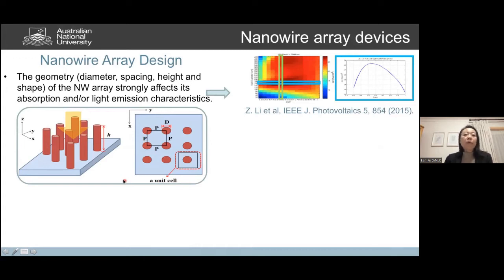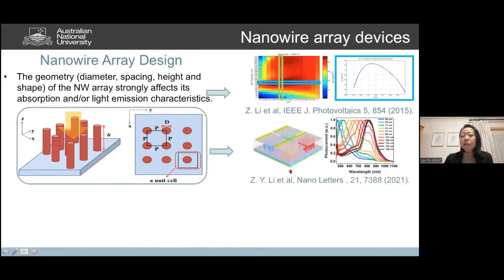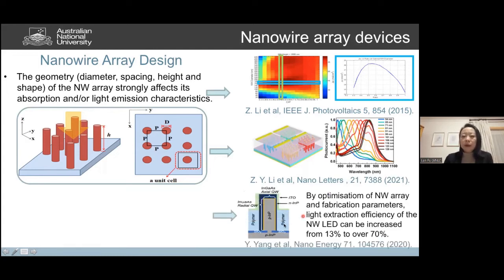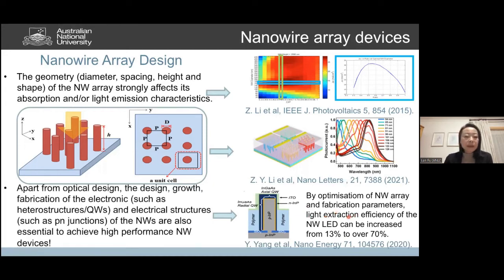We do numerical simulation to design nanowire arrays with good absorption, to achieve broadband absorption in solar cells. We've also shown that by tuning the diameter of nanowires, we can grow a nanowire array through the same epitaxial growth that produces photodetectors with a multi-wavelength response. We have also shown that by optimizing the nanowire array and fabrication parameters, we can enhance the nanowire LED light extraction efficiency from 13% to over 70%.